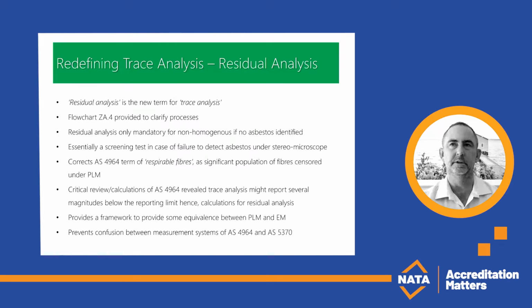And this is where only electron microscopy can detect respirable fibres, and it addresses the limitation in AS 4964, which inaccurately suggests that respirable fibres can be identified under trace analysis. So the same procedural framework is applied to all 3 analytical techniques to ensure consistency across the 3 methods. Another key aspect is that residual analysis is only mandatory if asbestos is not detected in non-homogeneous materials. Otherwise, it remains optional.